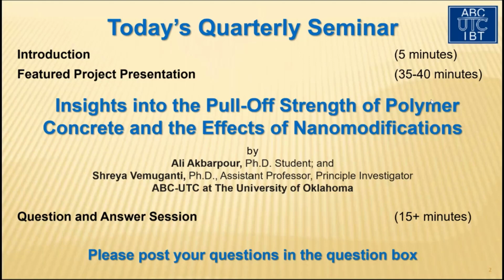Now, the second part of the question had CNTs. So carbon nanotubes, if I look at just the structure, they're very, very small materials. We are talking about each single CNT having a length of about 15 micron and a diameter of about 13 nanometer. So we're talking about tiny particles if you take a single nanoparticle. So they are potentially flying and become aerosols if not properly mixed. So during mixing, it's suggested to have some kind of PPE in place to carry on with the mixture.